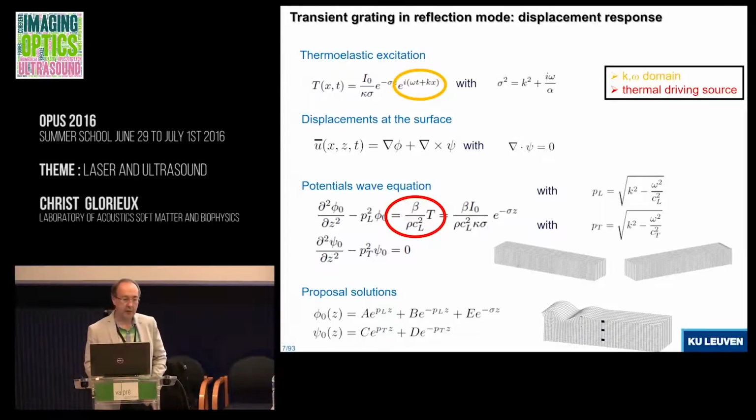This is just to show that you can apply the same thing, not for bulk excitation where you cross 2 laser beams in the middle of a sample, but as we are doing at the surface, the things become a little bit more complicated. Besides longitudinal waves, we also excite shear waves. So these are longitudinal waves and these are shear waves, and if you mix them in a natural way at the surface, you get these Rayleigh waves, surface waves, as you can see here. The speed of the Rayleigh wave is typically a bit slower than the speed of the shear wave, but the longitudinal wave is also a determining factor.